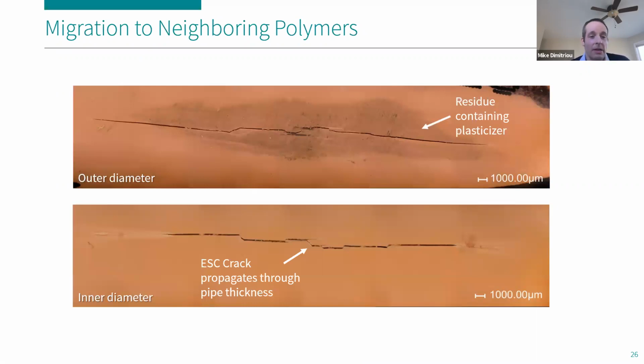And to give you an example, here is a CPVC pipe that we are looking at in the top image from the outside, the outer diameter of the pipe. This would be what you would see standing next to the pipe in use. And what you can see is a long jagged crack along the length of the pipe that has started to grow. And what has happened in this situation is you see this black residue that in fact contains plasticizer due to contact with another material that contained plasticizer. And this has initiated a crack due to environmental stress cracking. And this crack has in fact propagated all the way through to the inner diameter, which of course is undesirable for any sort of pipe application. With sufficient pressure or time, this crack may expand and may eventually lead to a rupture of this pipe.